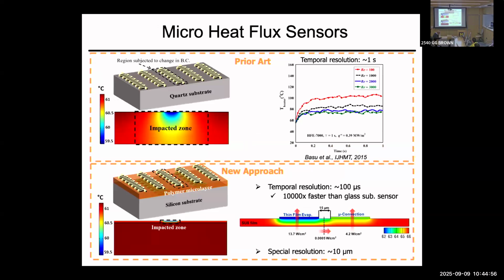So years ago, when I was a PhD student, I was struggling with this for years. And I was following what everybody else was following. And I wrote a paper and got rejected because it was just not the right way. What I was claiming was not the case. So the community, going back to basically the 60s, decided to use a low conductivity substrate and apply the heater here. So the assumption was that heat will go less inside the substrate and will end up in the fluid. So now they know the heat flux. But the problem is that this is a simulation we did, which initially we assumed that we have a single phase heat transfer coefficient.